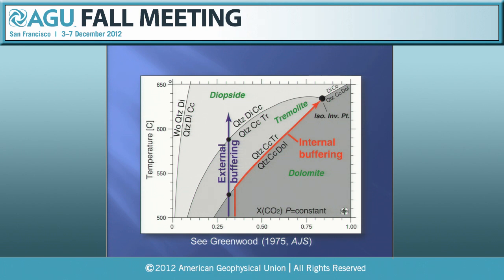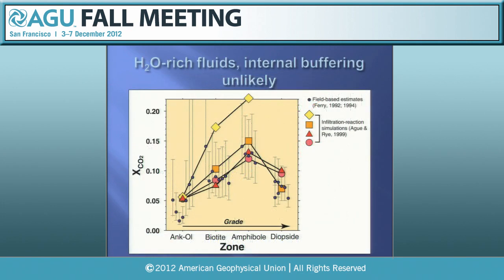Now, the truth probably lies somewhere in between here. One thing I can say is that there's been a move in some circles petrologically in recent years to consider every rock as being internally buffered. But we can rule that out very easily for these rocks, because internal buffering predicts very high CO2 values at maximum reaction progress. And if you actually look at field-based estimates of the mole fraction of CO2 as a function of grade, the dark circles here, you can see that those estimates are all less than about 15% CO2 in the fluid. And the only way you can really reproduce these kinds of numbers is if you have infiltration and reaction occurring simultaneously. All right? And that's what these colored symbols show. They match the field data quite well.